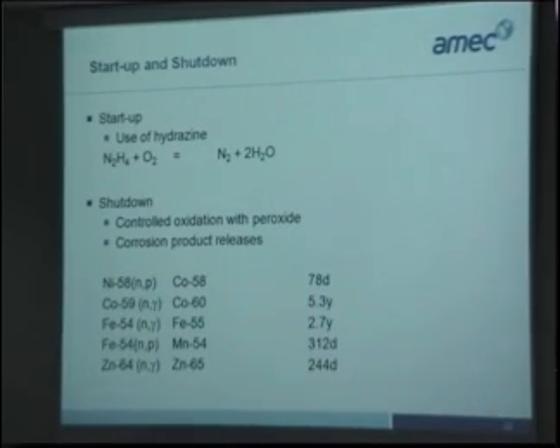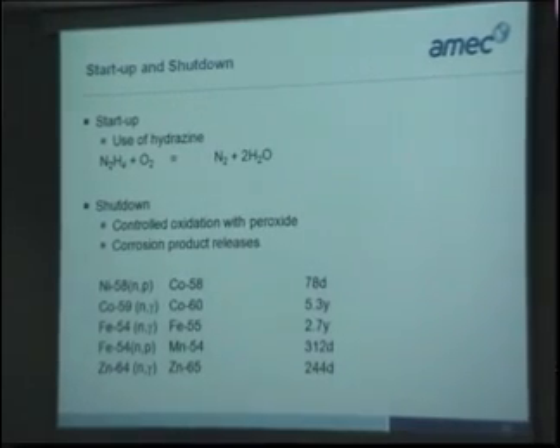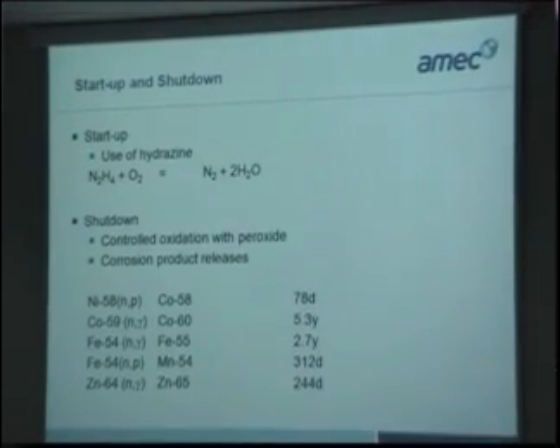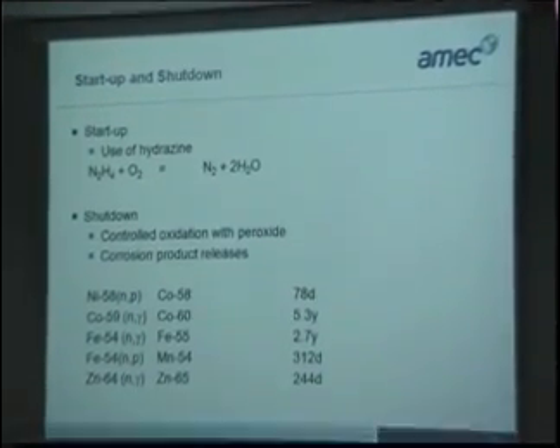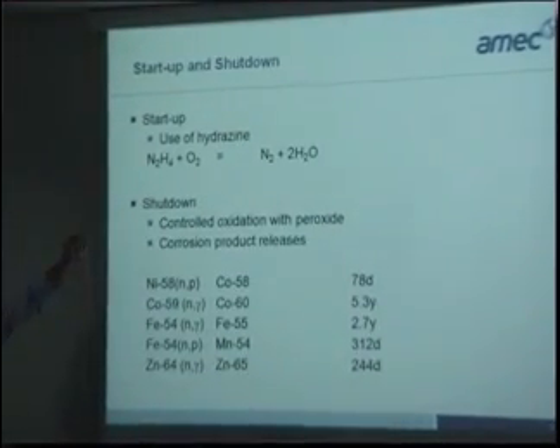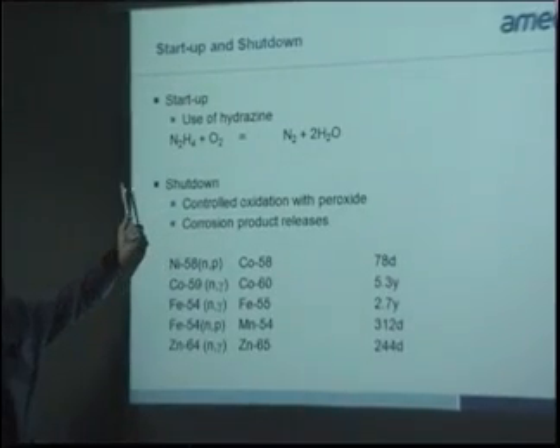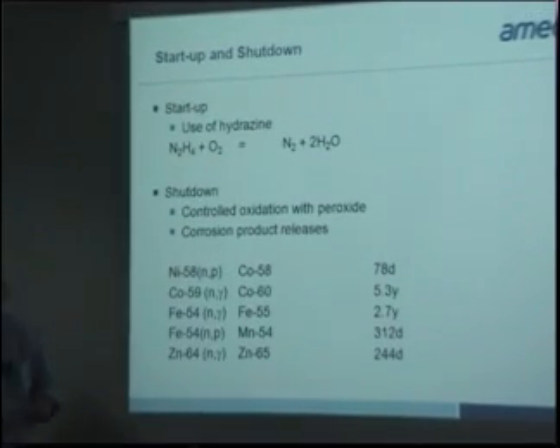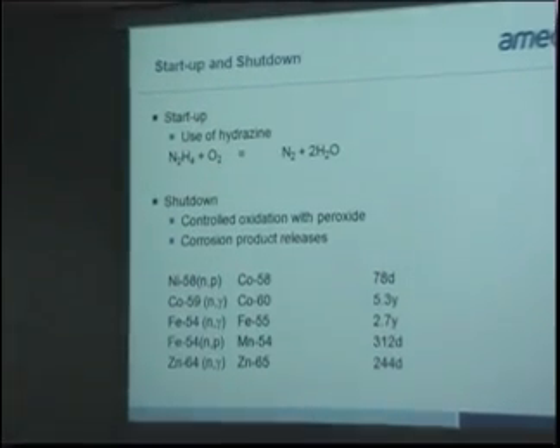At startup, we'll do it in the order on there. At startup, you're taking a cold oxidising coolant up to a hot reducing coolant. And apart from the usual vacuum deaeration techniques, we use hydrazine to actually dose at startup, because that's an oxygen scavenger, and you produce nitrogen and water, which are quite acceptable.